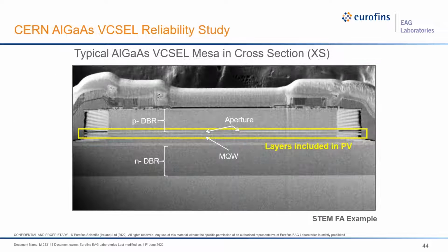This slide shows a cross-section of a focused ion beam cut into a failed VCSEL from the ATLAS detector. The aperture is noted in the center of the image, just above the multi-quantum well active region. The PDBR and the NDBR are also shown. The portion of the device shown in the yellow box will be shown in greater detail once this portion of the sample has been lifted out of the VCSEL.